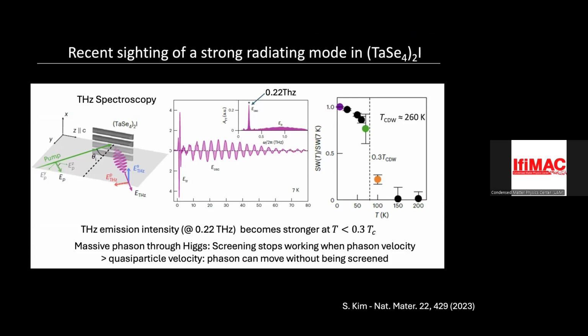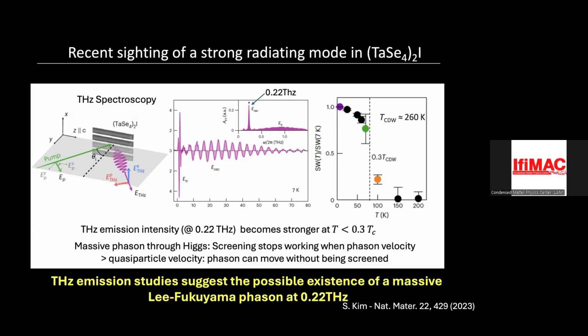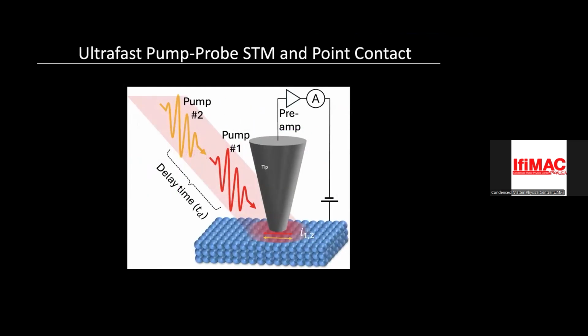Okay, so the question is, of course, if this is true, then we should be able to see it in STM. We should be able to see current oscillations associated with this phase mode. They're just seeing the radiation, right? So this is now our measurement. The data I'm going to show you, I have both tunneling data and we also push the tip into the sample. To do temperature-dependent measurements, we use point contact because otherwise the tip keeps changing at different temperatures, and we really want to compare the intensity of this peak at different temperatures. But let me just show you the data.